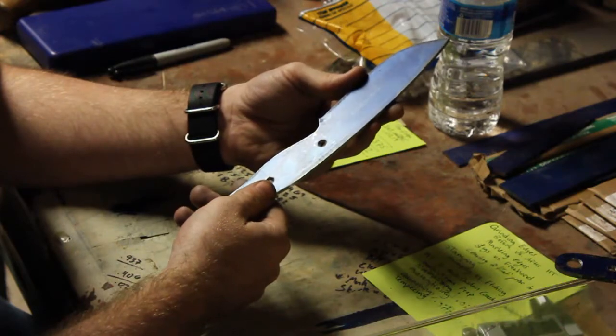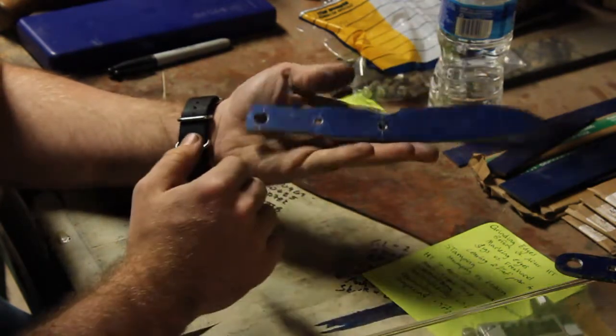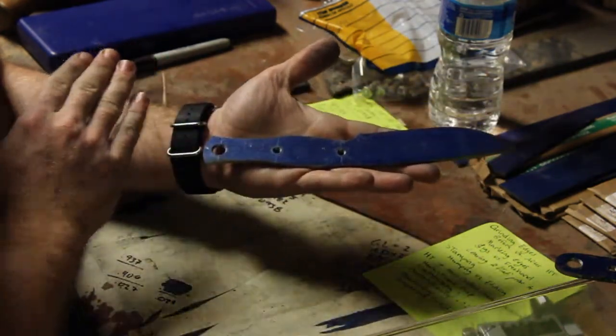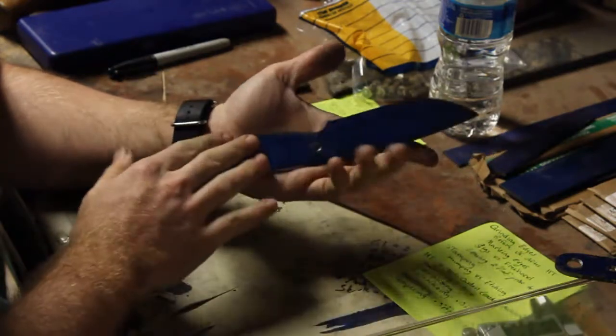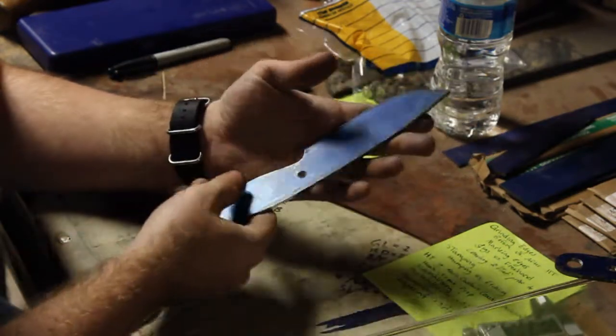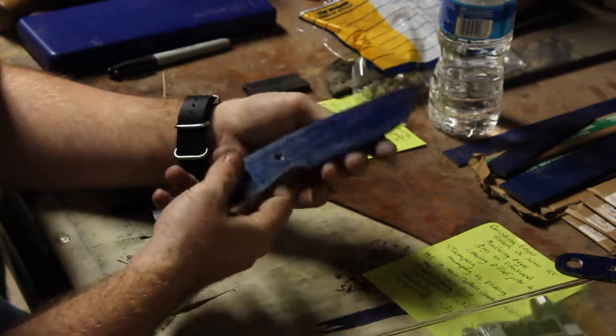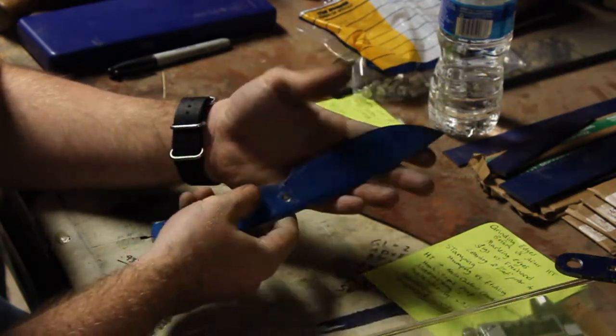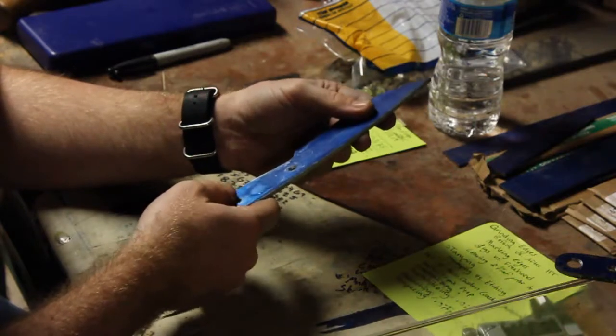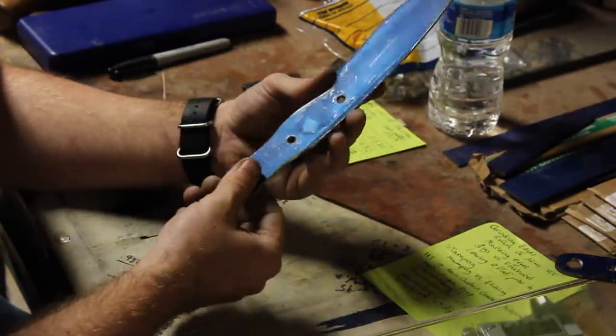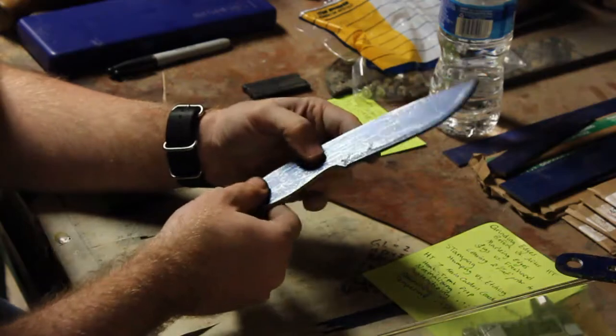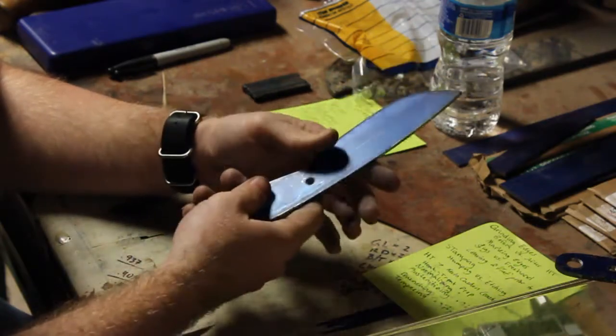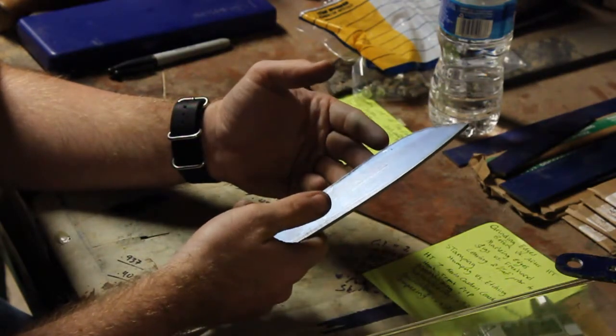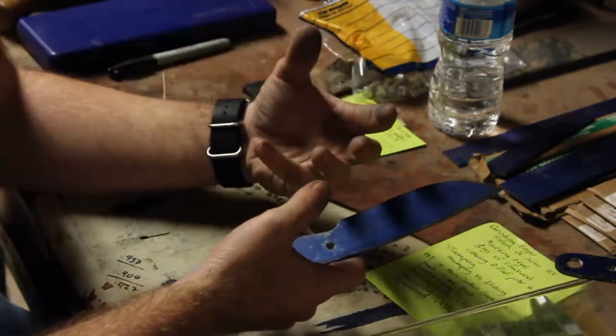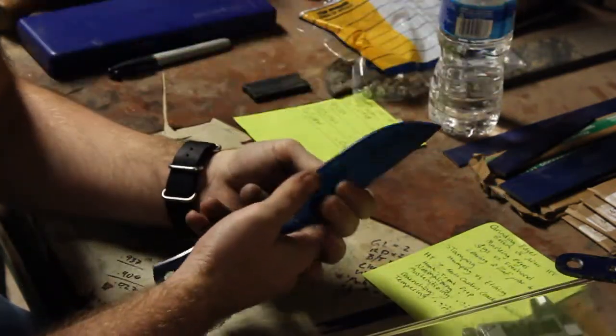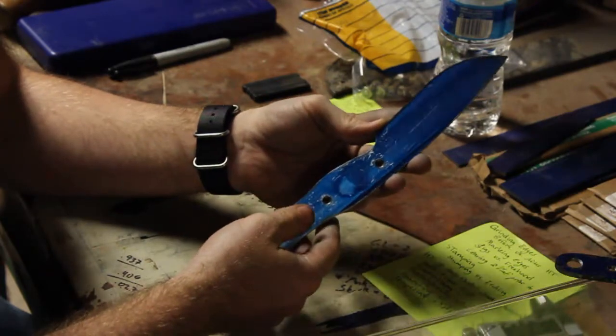But before I actually begin the heat treating process, I prep the knives. I sand off all the dye, and then I bring the knife up to at least 120 grit or higher if it's going to be a polished finished knife. The next thing that I do is I normalize the blades. Normalizing will be familiar to those of you that hammer forge. It's a type of stress relieving, but it's above and beyond the standard stress relief cycle.